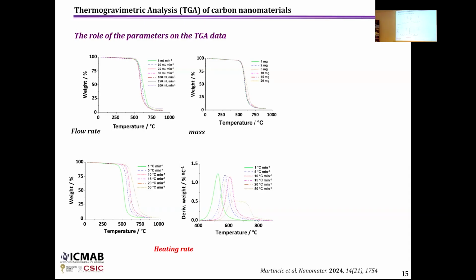So in this study, what we did was evaluate the thermal analysis of reference samples. In this case, these are references of carbon nanotubes, and we changed flow rate, mass employed for the characterization, and also heating rate. In the case of flow and the mass of the system, we didn't observe important variations. Of course, this mass also is related to the volume of the sample. So if we have samples with low density, we will need more sample inside the crucible, and then we will need to be careful about the amount of sample we put. But in the case of the heating rate employed for the characterization, there was a very big effect when increasing the rate used for TGA.